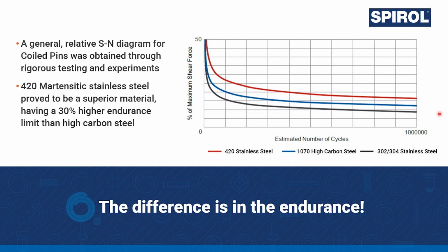Austenitic's performance is worse at only about 8.5% of its total shear strength. And keep in mind its shear strength is lower to begin with. Martensitic stainless steel outperforms even high carbon steel and can reach infinite life at as much as 16% of its total shear strength. These are general numbers for a very general scenario, and as we've discussed, even slight changes to operating conditions will yield different results.